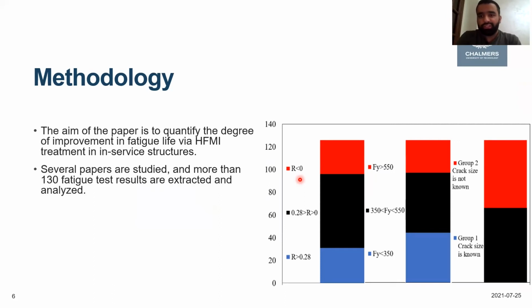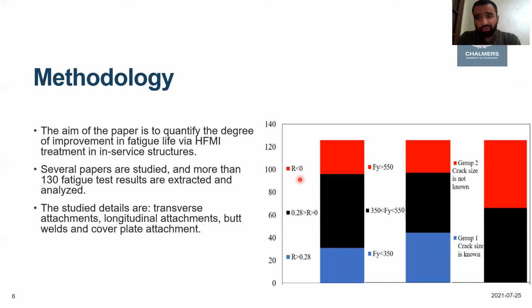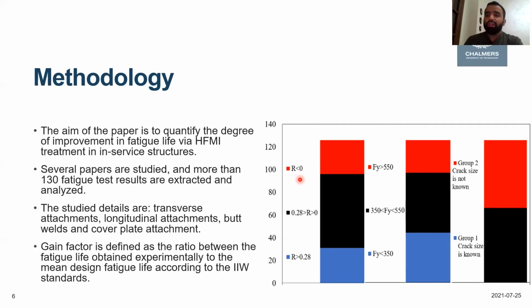So how I did that, it's a simple literature study. I've collected more than 130 fatigue test results from several research papers, and we analyzed them together. So the study also includes different types of details, which are of interest for bridge engineers, such as transverse attachment, longitudinal attachment, butt welds, and cover plate attachments. Finally, we use something we call the gain factor in fatigue life, which is a ratio between the fatigue life obtained experimentally for cracked or in-service structures in the lab, divided by the design fatigue life according to the IIW standards and recommendations.